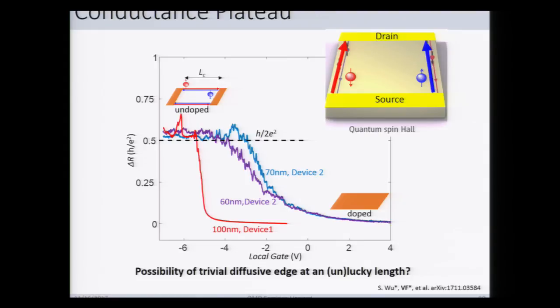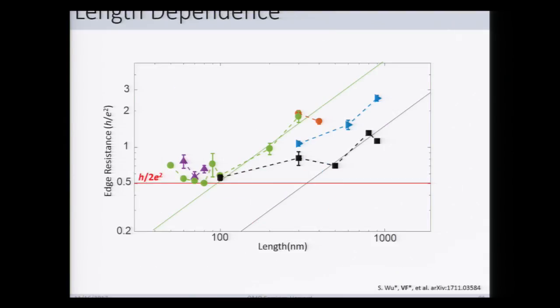Now, it's always possible that these modes are not actually ballistic or close to ballistic, but instead some trivial diffusive edge of some given length that happens to give you this value of resistance. And so what's advantageous about the design I showed you with all of these different gates is that a single device can give you multiple different channel lengths. What we show here is the edge resistance as a function of length on log-log form. Each color represents a different device, and I'll draw your attention specifically to the green and black data points, which represent a different gate that we use on that device. And at long length scales, we would see that the edge resistance is generally increasing, but it does not follow Ohm's law and instead starts to saturate, in both cases, towards this value of h/2e squared that you would expect for short length scales on such devices.